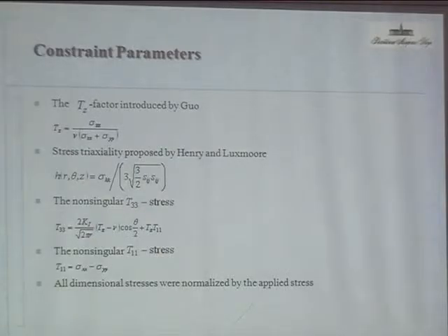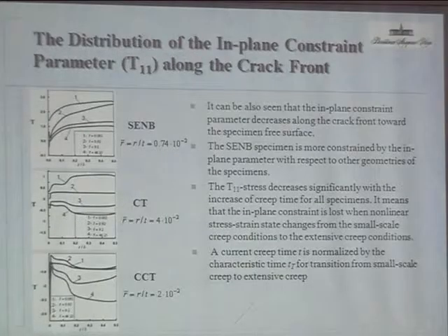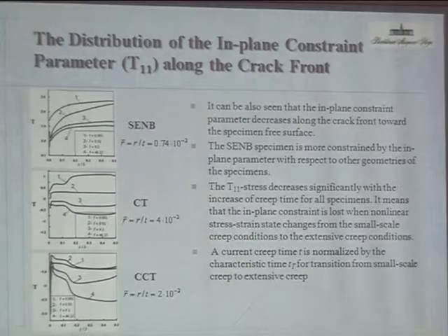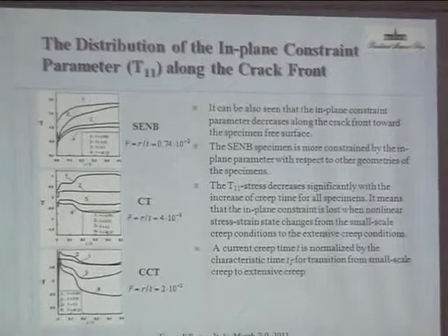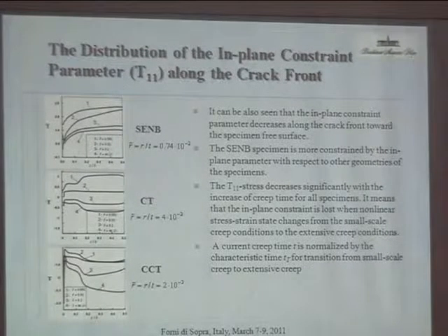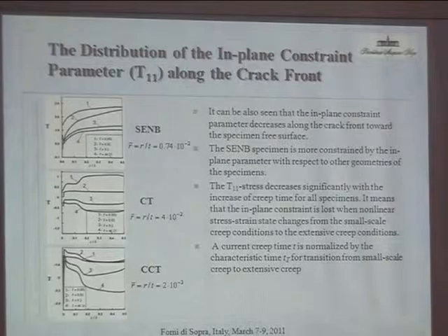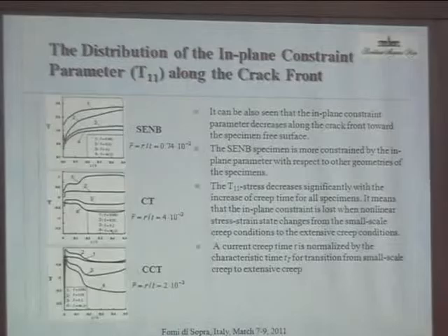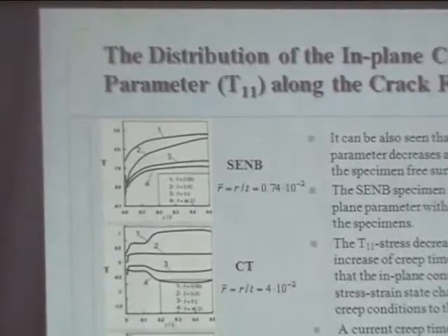In our research, we used a few constraint parameters. The T-Z factor introduced by Guo. You can see this equation. A stress triaxiality proposed by Henry and Luxmoore. And the non-singular T33 stress, which can be calculated using this very simple equation, which was obtained from the expansion of the stress field.